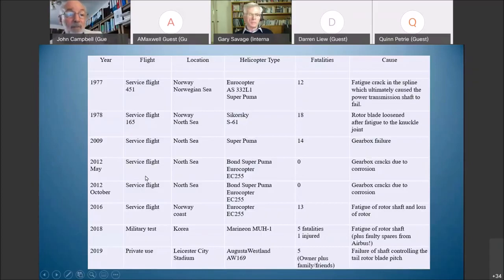And what's quite interesting is that these 2012 failures, when these helicopters, these Pumas, ditched in the North Sea, fortunately no one was killed because they landed nicely and the floats kept the helicopters afloat. But both of them failed from fatigue failures from corrosion pits, which, as we know, is not possible because the corrosion pit is too small to initiate a failure. And none of the world's experts could understand why these had failed, because the failure was impossible from a tiny, tiny pit.